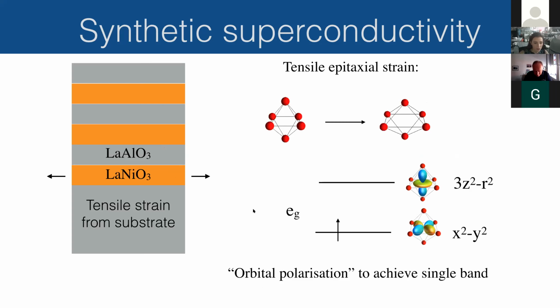Why is this? So the idea was that you would choose a substrate that applies a tensile strain. And then you would have, in the naive picture, the octahedron of oxygen that is now compressed out of plane and is stretched in plane like this. And this, combined with the orbital confinement that you expect from this kind of thin layer embedded in a superlattice structure with something inert, is that you could end up splitting in energy these orbitals that are in the EG manifold, so the out of plane orbital and the in plane orbital.